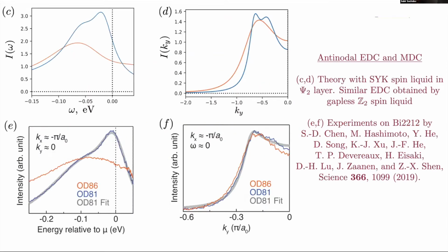And this calculation here, I didn't beat my drum about it too much because there's a lot of free parameters here. But in this calculation, that is what we were trying to do. We were trying to understand the full line shape. And to understand the line shape, we have to look at some low energy scattering. And we said, well, let's assume the low energy scattering is from the spin liquid. And we get reasonable fits. So let's just leave it at that. But this is by no means conclusive.